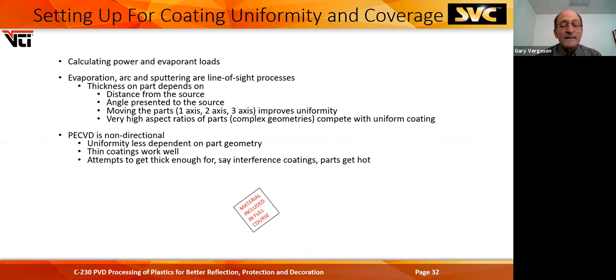Thickness of the coating you're going to put on the part depends on your distance, the angle, whether you're doing it in a drum, simple planetary or three-axis rotation. Three-axis greatly improves uniformity, and it's used mostly on things like cutting tools and tribological coatings. Very high aspect ratios, parts that are small in diameter and really deep, are problematic to get a usable thickness coating down on that part.